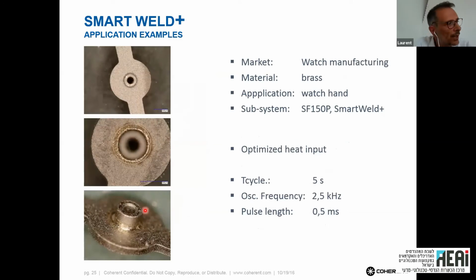Brass. Brass is not easy to weld with laser. Very difficult. So again, in this case, specific pattern, it was a circle, but in the circle a very, very small sinusoid. And we are working in pulse mode 2. And at the end, we are able to have a very, very nice result. If you can see here on the screen, on the picture, it's quite smooth. And no cracks, no explosion.